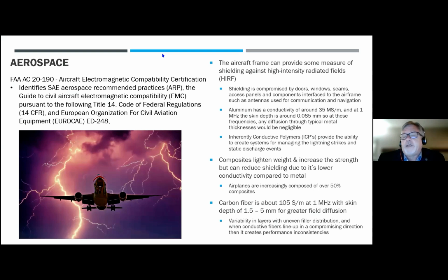For example, if lightning hits the aircraft, then the electrical conductivity is not going to be evenly distributed and could create some issues within the aircraft itself. So typically, aluminum has a conductivity around 35 megasiemens per meter, and at 1 megahertz, the skin depth is around 0.085 millimeters. So at these frequencies, any diffusion for typical metal thickness can be negligible.